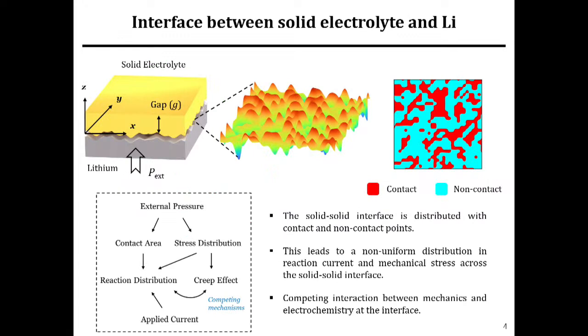To start with, the major challenge lies in the morphological stability of the interface between the solid electrolyte and the lithium metal anode. As opposed to liquid electrolyte systems that offer good wettability of the electrolyte over the metal electrode, solid-solid interfaces are often limited by poor wettability. These interfaces can also encompass a wide range of heterogeneities and defects, whose implications I'm going to discuss in the coming slides.